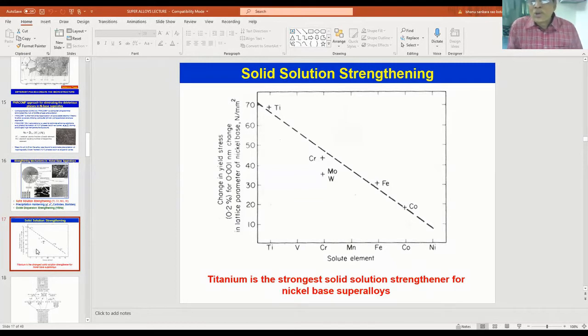Now, solid solution strengthening, you see how the change in yield strength will be occurring in case of superalloys. All the elements have been plotted here: titanium, cobalt, iron, molybdenum, tungsten, chromium, and then the change in yield strength that is occurring. There will be a change in lattice parameter by adding the solid solution elements. Now titanium is the most potent solid solution strengthener. But please remember, titanium is a very desirable element for forming the gamma prime in the material, which is the major strengthening phase. So the role of titanium, you can see that it plays in three ways.